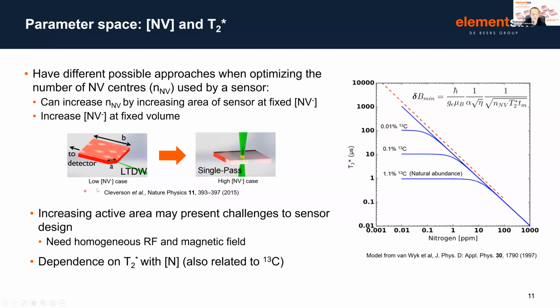Now, there are advantages and disadvantages of these two approaches. And one of the downsides potentially with the low NV case is that you have the challenge of increasing the active area of your sensor. What that means is you need a homogeneous RF and bias magnetic field across the volume that you're using. The other critical thing that I need to get across is this idea that the coherence time is related and dependent on the amount of nitrogen that is present in the material and also the amount of carbon-13. Now, carbon-13 has a nuclear spin, so it also acts to dephase NV centers.